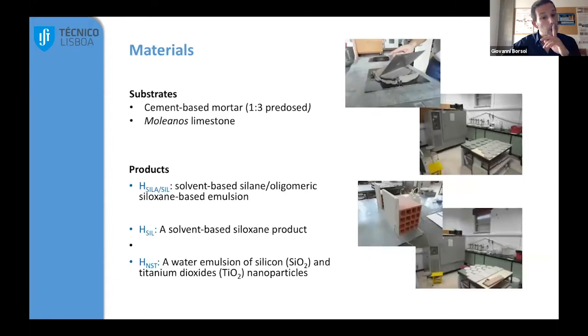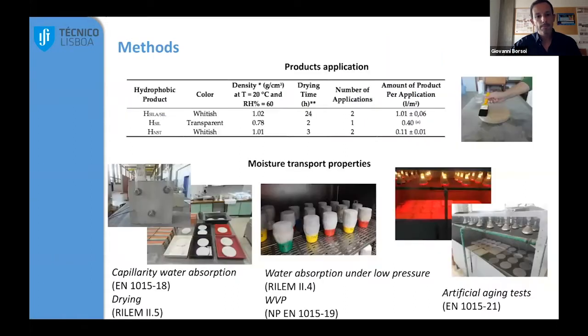So we are basically accelerating the decay of the material, because those irreversible treatments cannot be taken out of the treated materials. In this research, we have focused on a few materials: cement-based, a couple of materials actually, a limestone and a mortar. We have also focused on silane or siloxane products, a siloxane product, and finally, the third product is an emulsion of silicon and titanium oxide nanoparticles. Basically, those are the methods. We applied the materials with a specific process, and all the details are in the special issue. I will just give an overview.